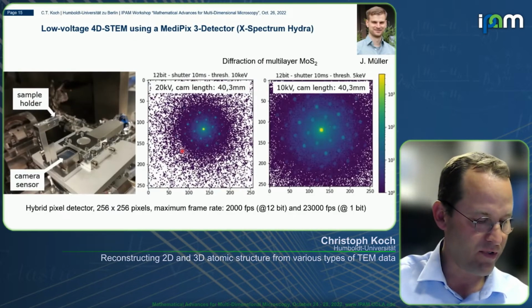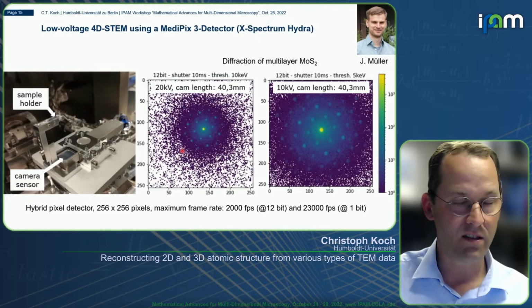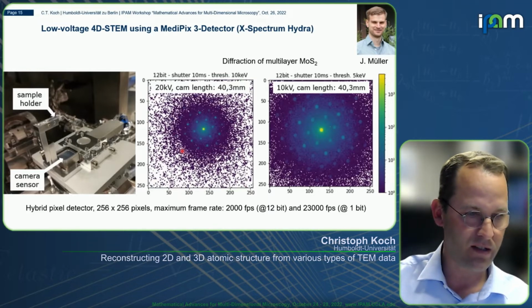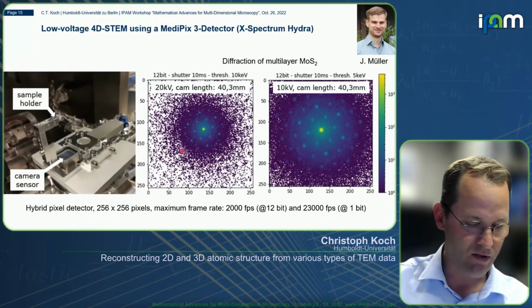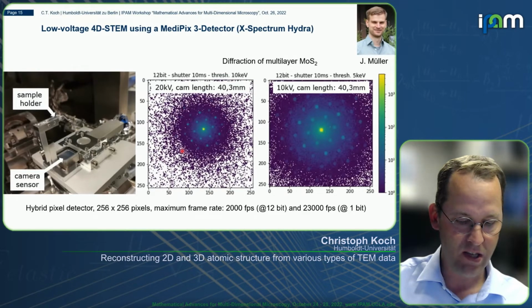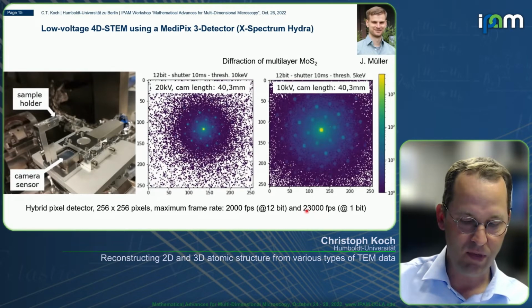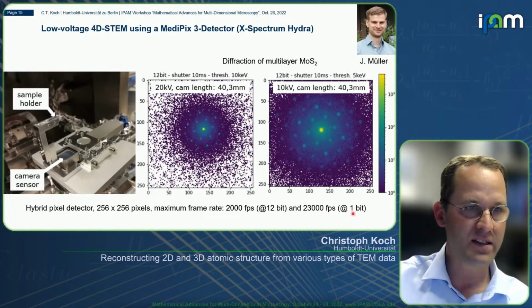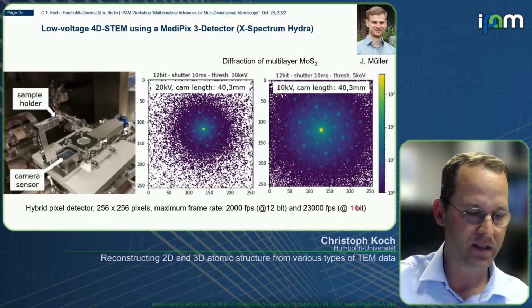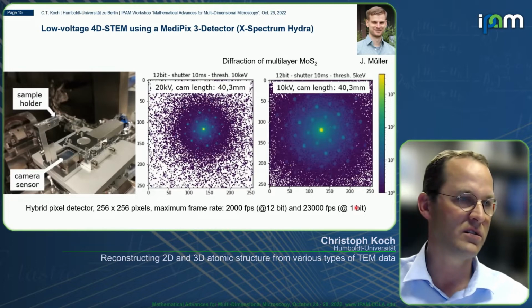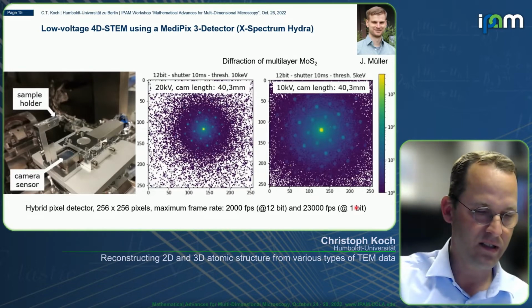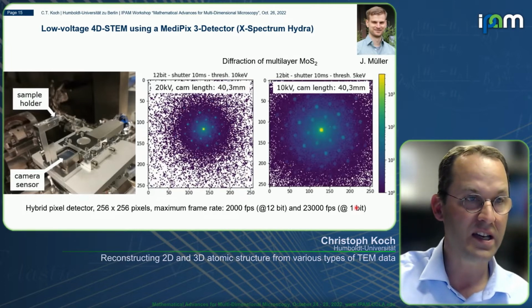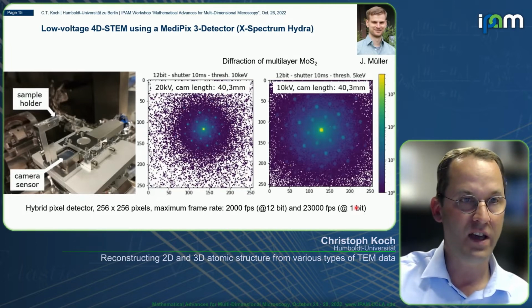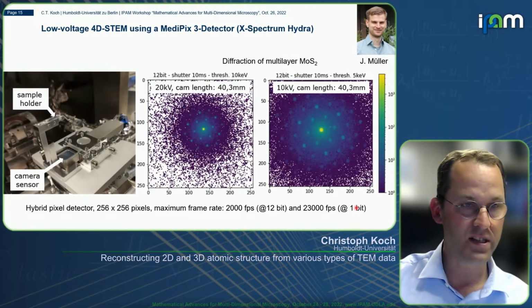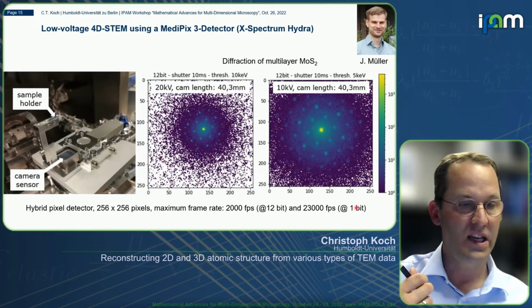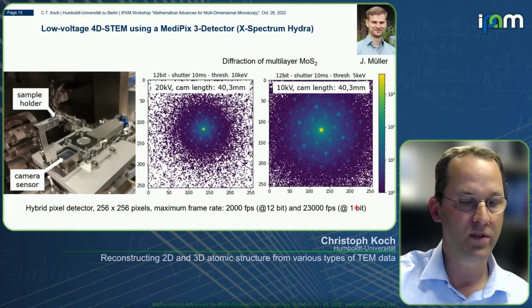So just to show, and then I will stop with the hardware, you can also do this with direct electron detectors. So this is one of these Medipix detectors, which can go to very high frame rates, for example, 23,000 frames per second if you reduce your bit depth to only 1 bit. And if you scan very fast, I guess at least in some labs this has been shown to be sufficient because you don't get so many electrons. But that's just to show that this can also be done inside an SEM, which gives you the advantage of having very low noise, actually no readout noise of your detector, and just the Poisson noise that you model with most of your statistics assumptions anyway.